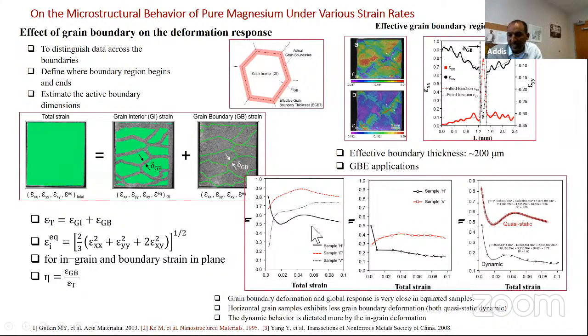So eta is the strain in the grain boundary over the total. As you see, for different specimens, horizontal, vertical, and equal-size specimens, the involvement of the grain boundary is different. The samples which have equal size actually have larger involvement of the grain compared to the others. But one thing confirmed here is that the quasi-static case has a larger grain